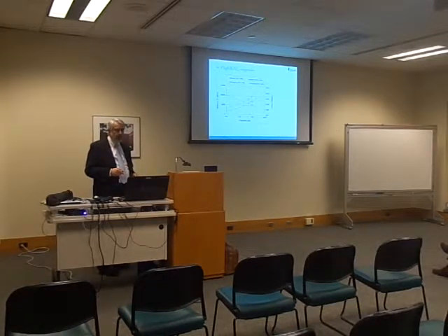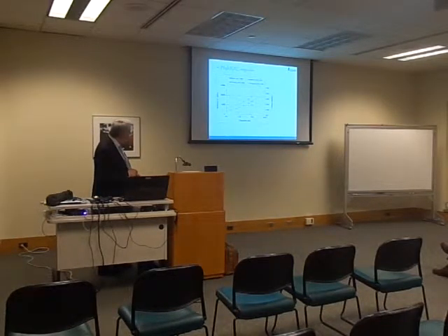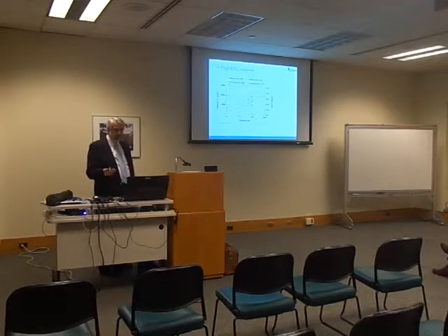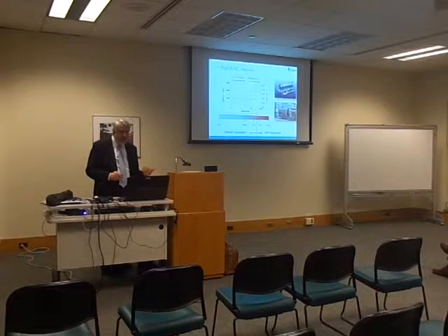Just an example, we played with changing the percentage of recycled material from 50 to 65%. So we see stiffness here in red and blue for one mix that we had with 50% recycled material, not rejuvenator. This is the red line here. And then just a 15% difference between those two, if you look at it in terms of stiffness change, is way out of proportion. The rule of thumb in the Netherlands at least is that up to about 65%, probably you can live with these high stiffnesses. Above that, you need rejuvenator. You need to bring the material back to where it was or midway there.